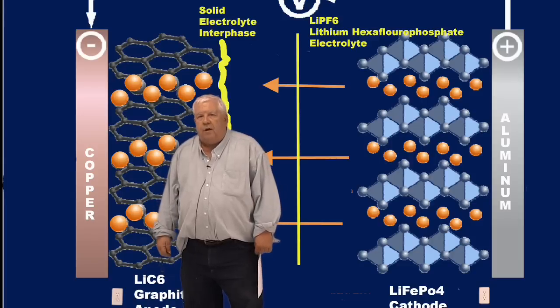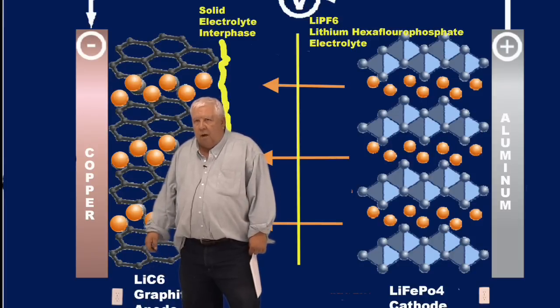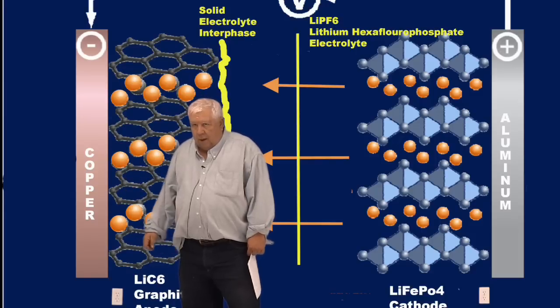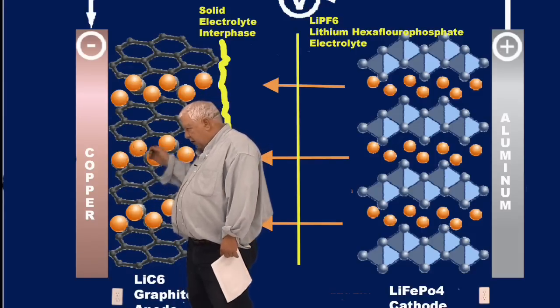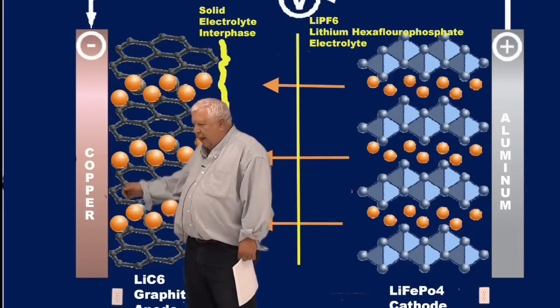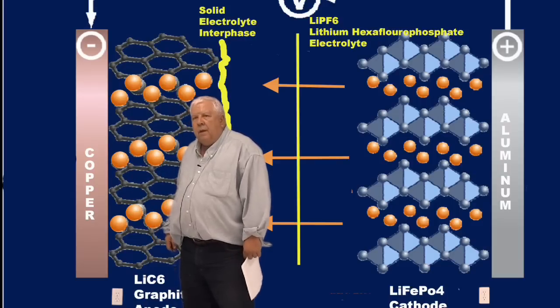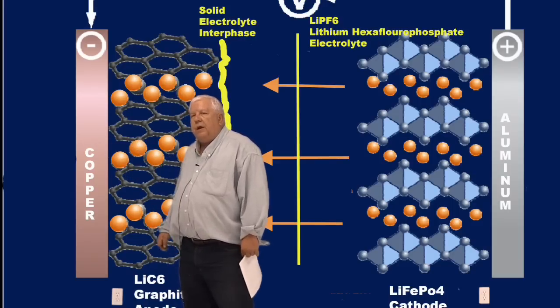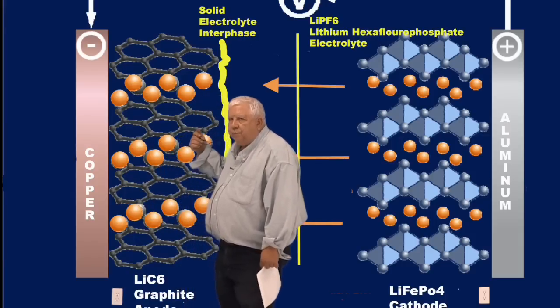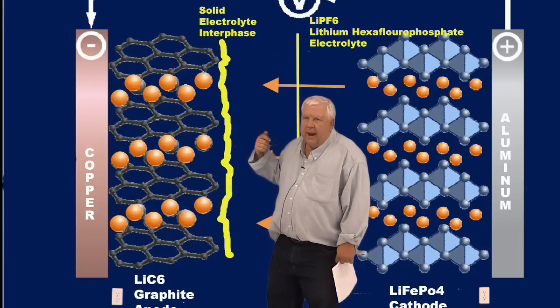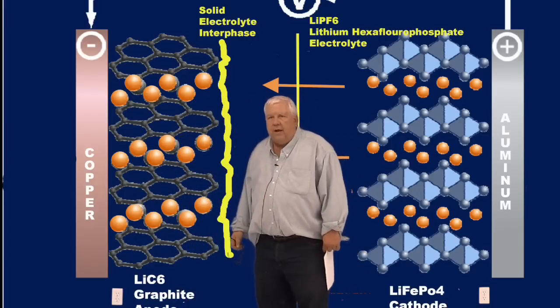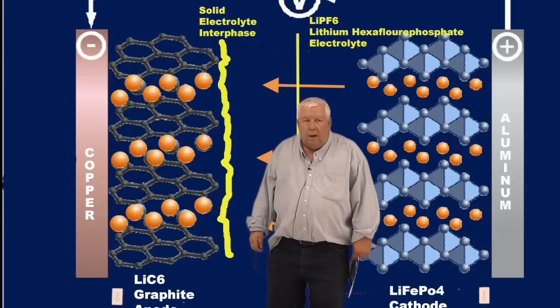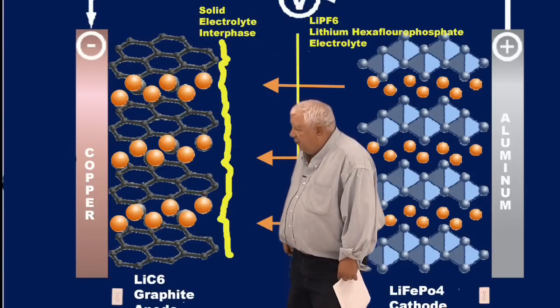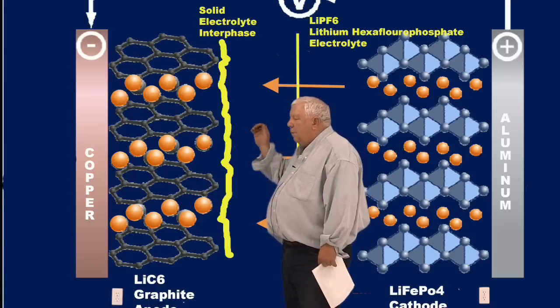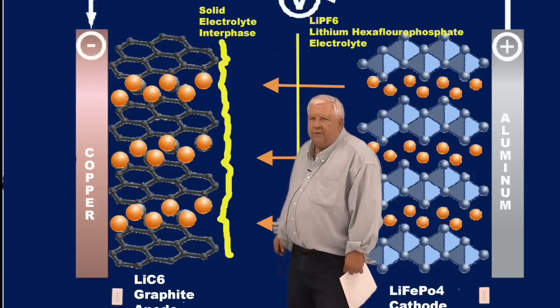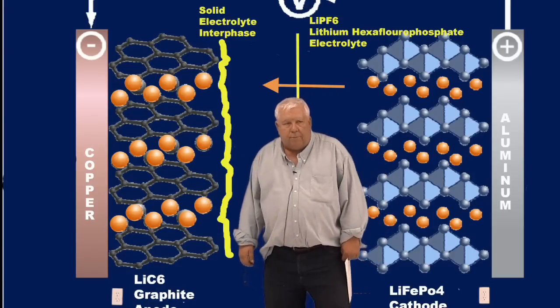And so over-discharge primarily is a function of copper plating on the SEI, and overcharge is primarily a function of lithium dendrite growth. A lot of people talk about copper shunts being involved out of here. Some, that copper plating can turn into dendrites and again puncture your separator. And if that happens, it shorts the cell. And so you have essentially the same effect on overcharge and over-discharge. Overcharge tends to be a buildup of lithium, and over-discharge tends to be a buildup of copper.